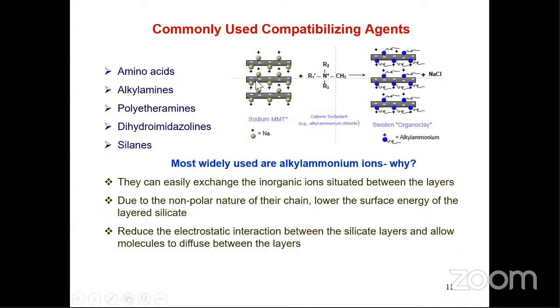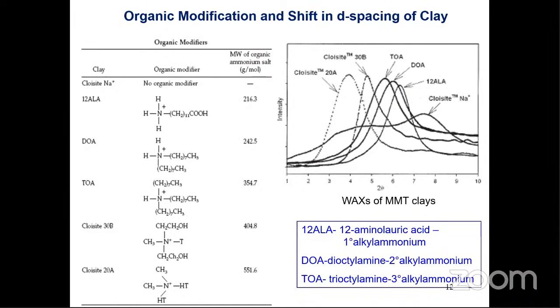This is clay, which is hydrophilic, and it interacts with a compatibilizing agent. Here is a tetraalkyl ammonium compound. You see the tetraalkyl ammonium compound gets into the intergalleries and the gallery space is increased. It's a very interesting slide. Look at this, this is a neat clay with very small gallery spacing.